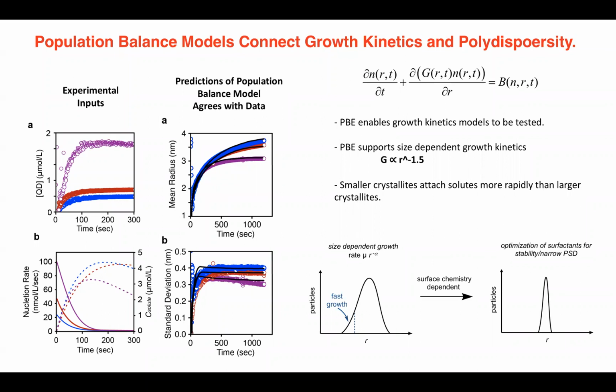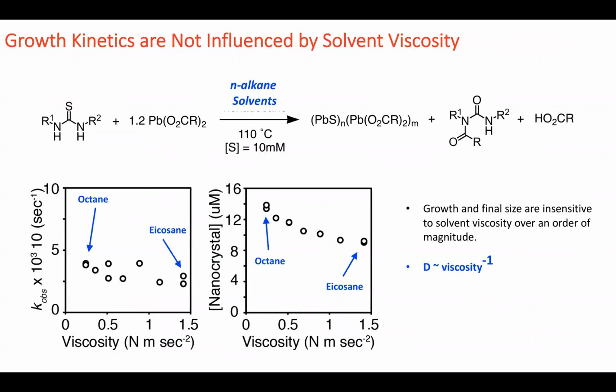The nucleation is really slow. They all turn out the same size at the end. You have to have this narrowing. The best, simplest fits are for a radius dependence of about r to the minus 1.5, but it could be higher than that actually. All right, so it's not diffusivity.